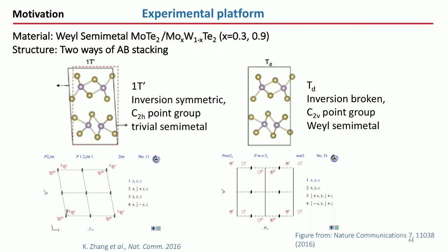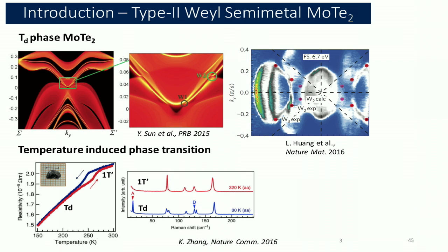So the recent discovery is that MoTe2 is a Weyl semimetal, as people figured out, in this Td phase, where you break the inversion symmetry. But this occurs below 250 Kelvin. Interestingly, you can also find these materials, MoWTe2, where you dope some tungsten, and this material becomes a Weyl semimetal even at room temperature. So now you can have all these quantum-type phenomena at room temperature. So this was the interesting discovery.